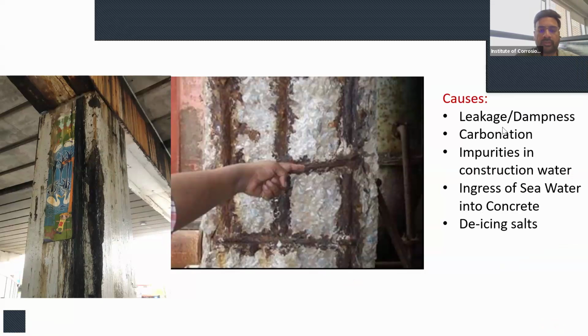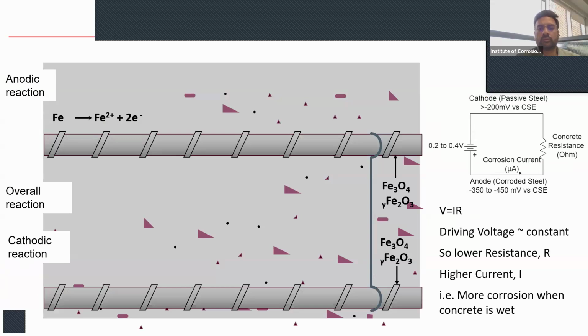And the major reasons for corrosion in reinforced concrete are leakage, dampness, carbonation. In India particularly, what we are seeing these days is a lot of corrosion happening in structures due to impurities in the construction water, which has led to severe corrosion in structures, ingress of seawater into concrete, and de-icing salts. So, in general, discussing the corrosion mechanism...